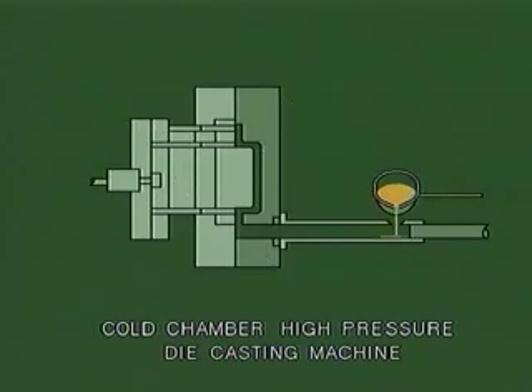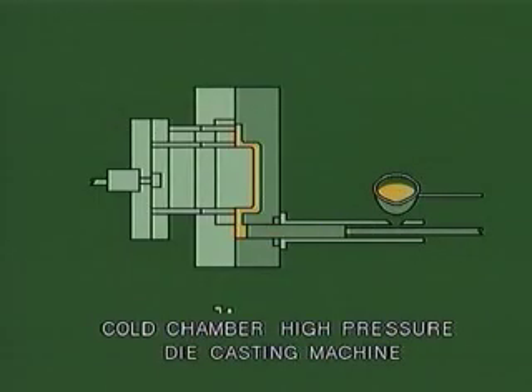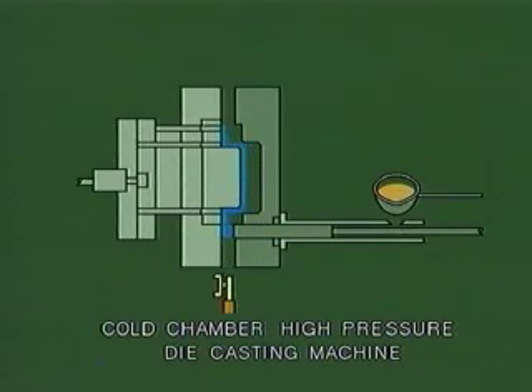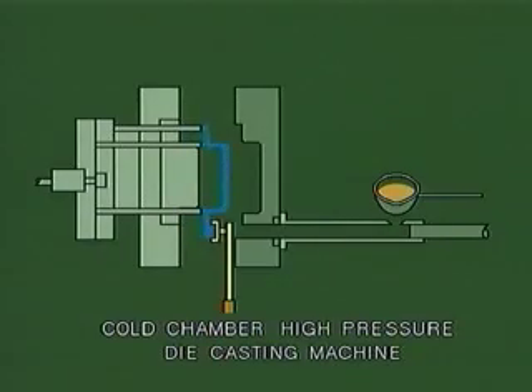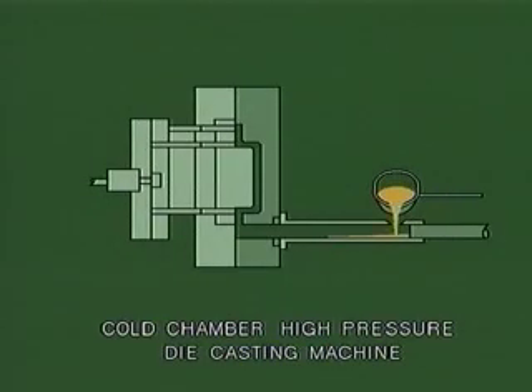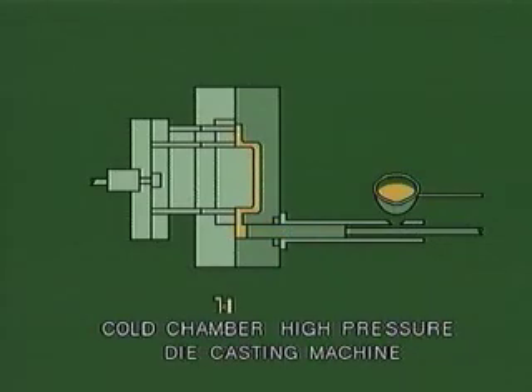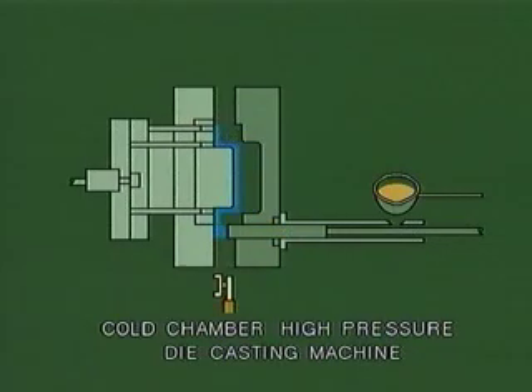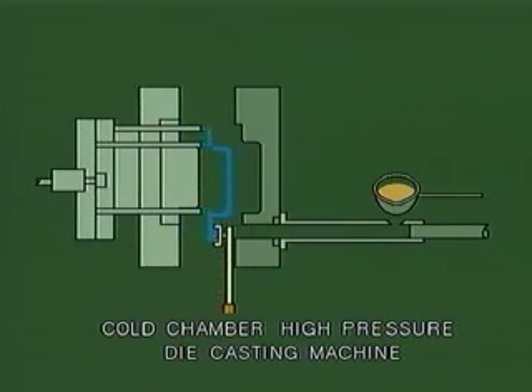Molten metal is poured into the chamber. The plunger forces the metal into the die at pressures of 100 megapascals or more. This gives rise to a very strong outer skin on the casting. The die cavity is sprayed with a water-based lubricant that cools the die and helps extend die life. Cold chamber high-pressure die castings can maintain high dimensional tolerances and excellent surface detail, but generally are not weldable or heat treatable.